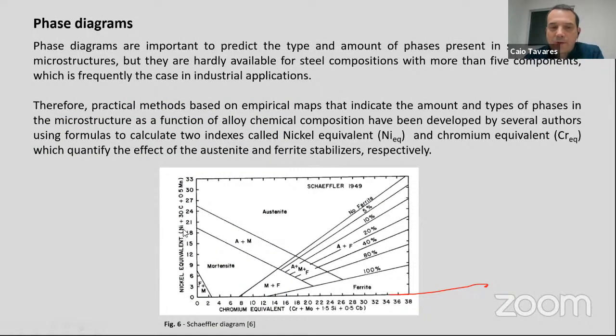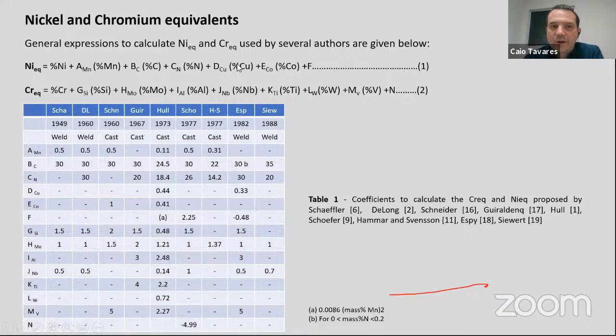For the formulas to calculate the nickel equivalent and chromium equivalent, there are a lot of expressions in the literature. I cited here 9 different authors that created different expressions to calculate the nickel equivalent and chromium equivalent. So they use different coefficients for each element. You see there is a big range of formulas by different authors in different years. Many of them are applied to welding, but some are applied to castings.